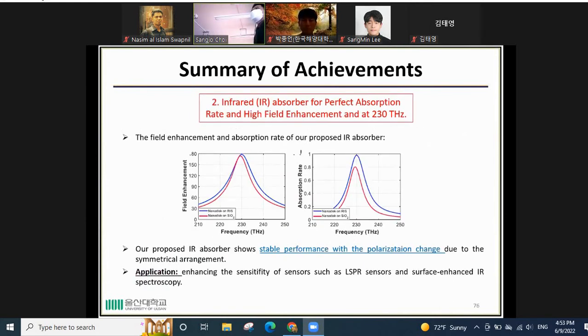And for the second one, for infrared absorber design, this is the field enhancement and absorption rate of our proposed infrared absorber. We see that nanodisks combined with RIS show higher field enhancement with perfect absorption compared to the nanodisks sitting on a silicon dioxide substrate. Also, our proposed IR absorber shows stable performance with polarization change because of the symmetrical alignment. So in the future, the application of the structure is to enhance the sensitivity of sensors such as LSPR sensors and surface enhanced IR spectroscopy.